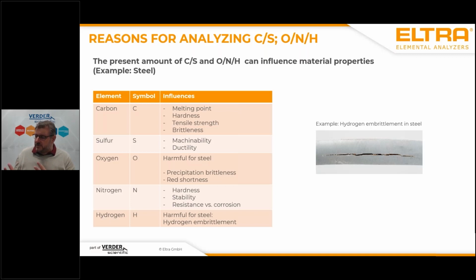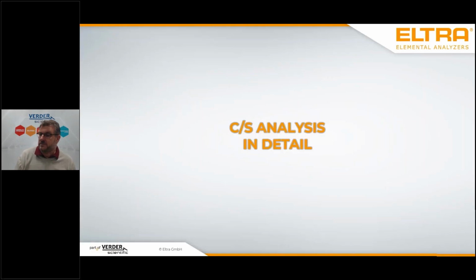You cannot predict which influence an element has for every matrix, but the general things are: carbon influences technical properties like melting points and hardness. Sulfur influences the machinability. Oxygen is an indicator for a bad tendency for corrosion. Nitrogen can influence the hardness. And as mentioned before, hydrogen can dramatically influence the stability of a product, which means, is this product really stable when you use it? For this reason, hydrogen analysis is highly recommended, especially for aerospace and medical applications.